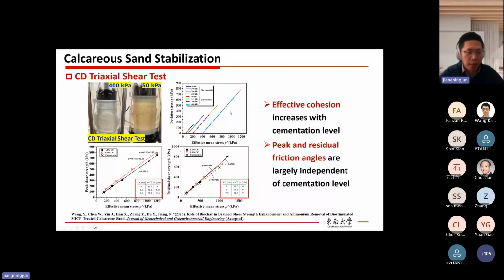Then based on the testing results, we obtained the failure envelope both at peak state and at the residual state. From the failure envelope, we could obtain the effective cohesion as well as the effective friction angle. At peak state, we can see that with the increase in the cementation content, the cohesion increases. At 9% cementation, the cohesion could reach more than 40 kPa. Then the effective friction angle is largely independent of cementation level.